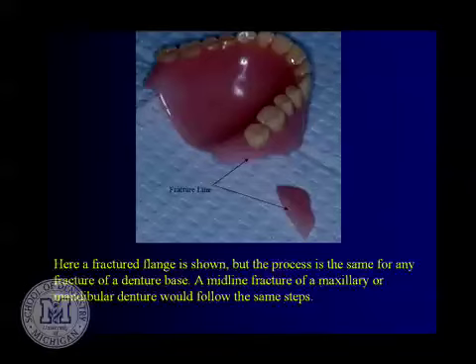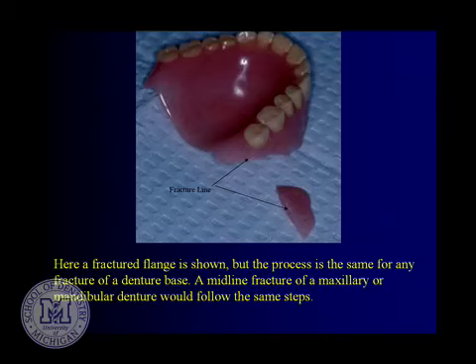Sometimes what makes this process more difficult: when polymethylmethacrylate breaks, it produces an extremely crisp and clean fracture plane, so the two pieces mate very perfectly. The exception is when patients try to repair their own denture with a glob of superglue. Superglue will actually melt the plastic a little bit, and patients figure if a little is good, a lot must be better—not true. The two pieces that would have mated together very nicely no longer fit.